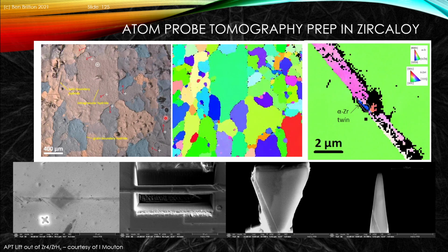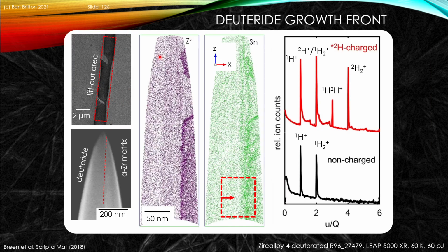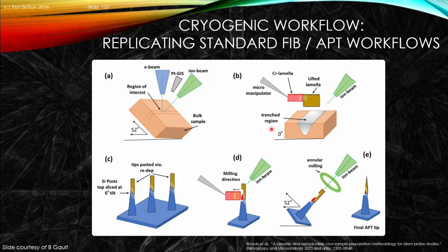But this is super powerful, so this is just showing this example where we did site-specific work, where we picked a series of different hydride metal interfaces, and we looked at a series of different hydride types in this particular work. This enabled us to do some really cool bits and pieces to start to look at effectively the decoration of iron and tin associated with hydride metal interfaces. And we did this specifically starting to look at different isotopes of hydrogen that were presented in this work.